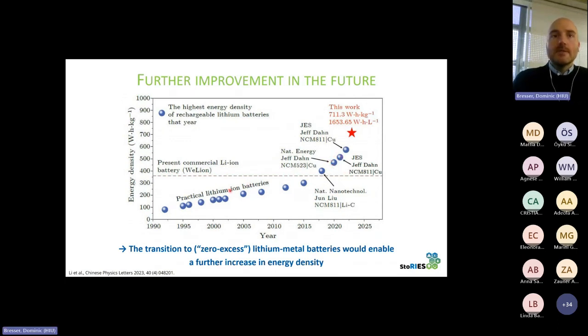So you see here the evolution in terms of time versus energy density in watt-hours per kilogram. And you see that practical lithium-ion batteries continuously increased their energy density. I think that's also something that is worthy to be highlighted. On average, I think we had like a 10% increase every year. And I think that's a very remarkable value, not only due to materials, but largely to engineering. But anyhow, the two have to work together.